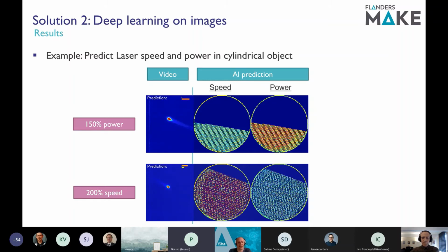On the other hand, if you, for example, change the speed by 200%, you also see here that the AI module predicts the power as being nominal, indicated by the green color, but the speed predicted too high. So if we see this kind of behavior, we know that the controller needs to reduce the speed in order to stay within the optimal parameter regime for getting optimal quality.